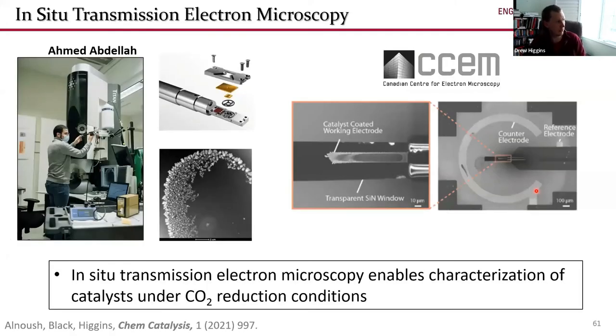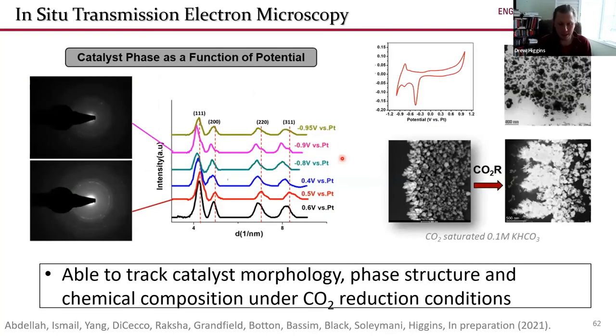And Ahmed Abdallah is also a PhD student in my group working on in situ characterization of electrochemical CO2 reduction catalysts using electron microscopy. So essentially taking these microchip reactors that have a working electrode, a counter electrode, and a reference electrode, depositing a catalyst onto that working electrode, flowing in an electrolyte, achieving electrochemical CO2 reduction conditions, and then characterizing the phase structure of the catalyst under CO2 reduction conditions, as well as the morphological changes occurring in this catalyst under electrochemical CO2 reduction conditions.